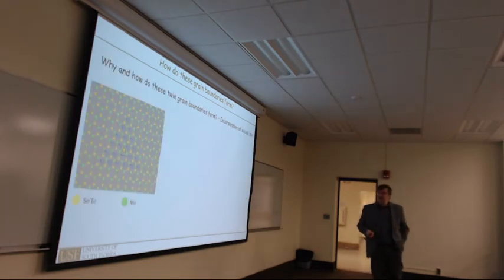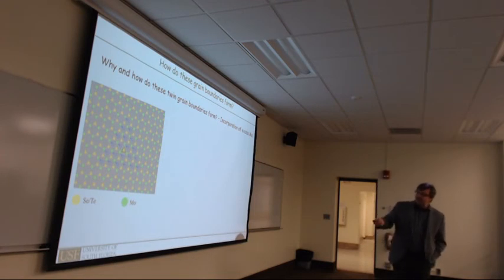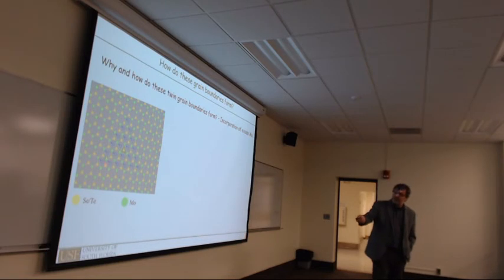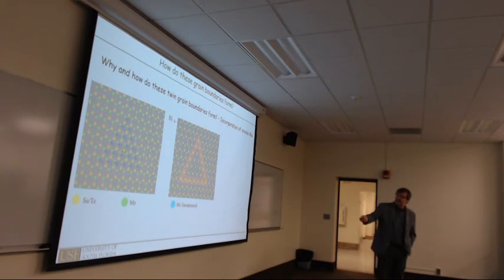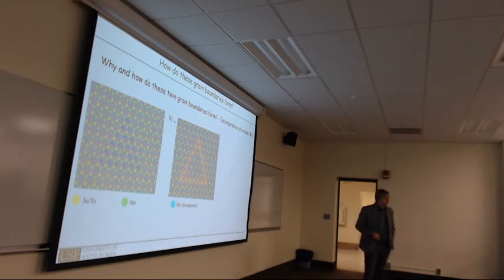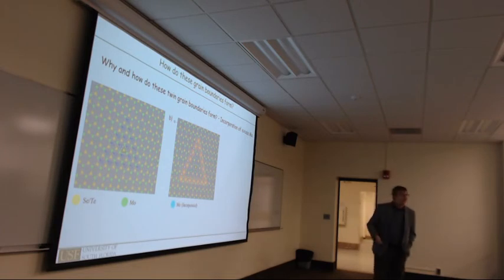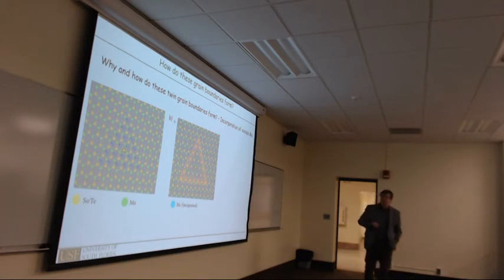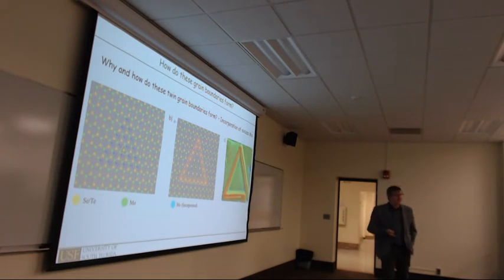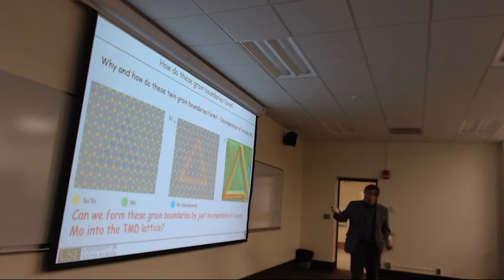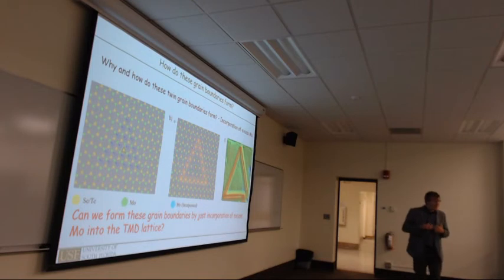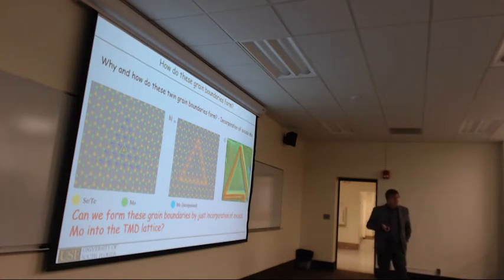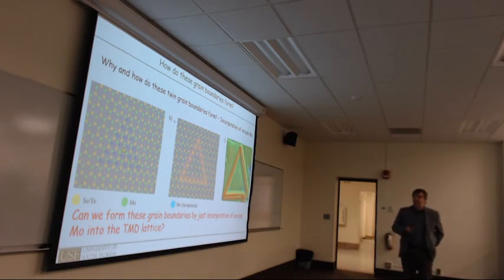So that gave us a simple idea. In a thought experiment, you can take your lattice and just translate part of the molybdenum sublattice by a fractional unit cell vector. If you do that, then you would form a twin boundary on this side, a twin boundary on that. Inside you form a twin, and then on this side you are left with missing molybdenum that you would need to fill in, and then you form a closed mirror twin grain boundary, which is triangular and is similar to what we see in STM. So the question then is, can we form these twin grain boundary loops just by incorporating excess molybdenum into the lattice? And is that why we get these dense networks if we grow with molecular beam epitaxy, that we just provide too much molybdenum?